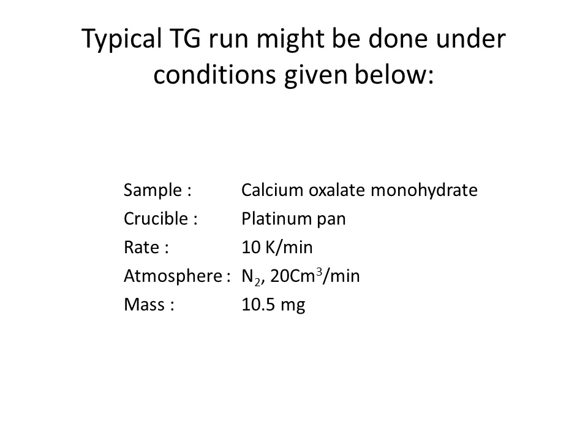Now this is just, for example, a typical thermogravimetric run that might be done under the following conditions. For example, the sample may be calcium oxalate monohydrate. The crucible used may be a platinum pan. The rate of temperature increase is 10 Kelvin per minute. The atmosphere which may be used could be nitrogen, and nitrogen is fed at the rate of 20 cubic centimeter per minute. And the mass of the sample used is 10.5 milligram. So this is just an example.